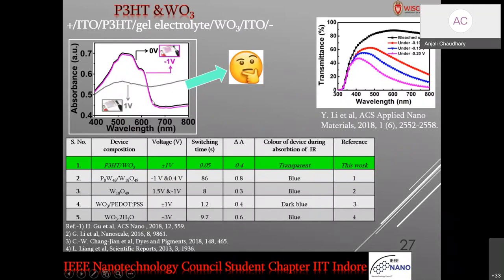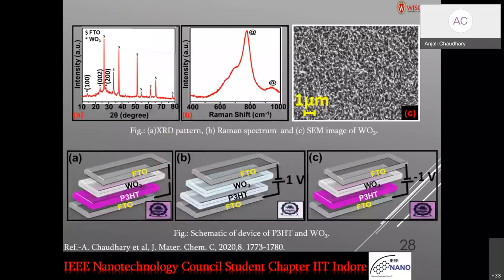During our experiment, we found that people use tungsten, but the problem with tungsten is that you get a blue color when you are switching it. So we have to restrict our choice to P3HT and tungsten. We combine them both together in a device. We have fabricated tungsten oxide using a hydrothermal process, and these are some characterizations of it: SEM, XRD, Raman, and all this.